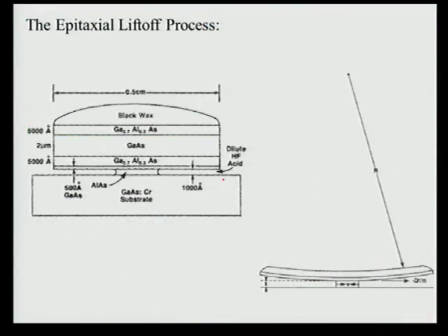Now, the key to making the gallium arsenide inexpensive is that the expense is coming from the very expensive gallium arsenide substrate. And the key then is to reuse the substrate and peel the solar cell. The solar cell is a very thin film on the substrate. It doesn't have to cost much. You peel it off, and then you reuse the substrate many, many times.